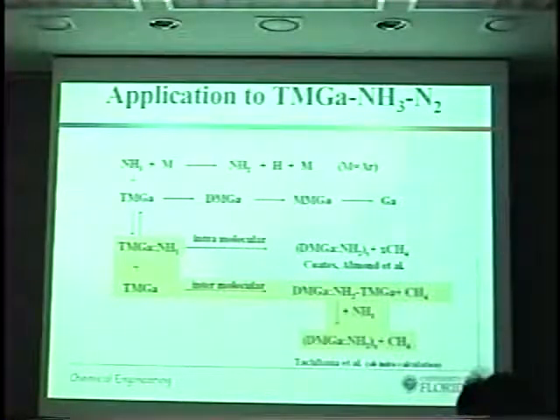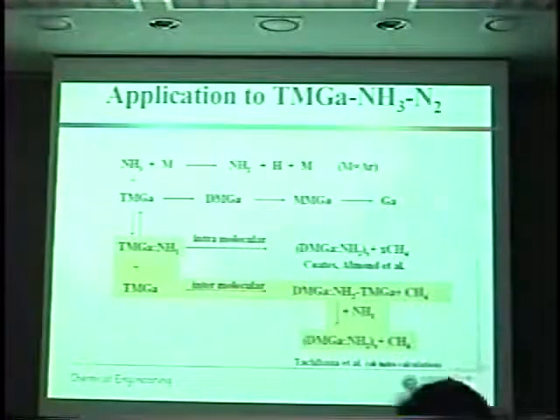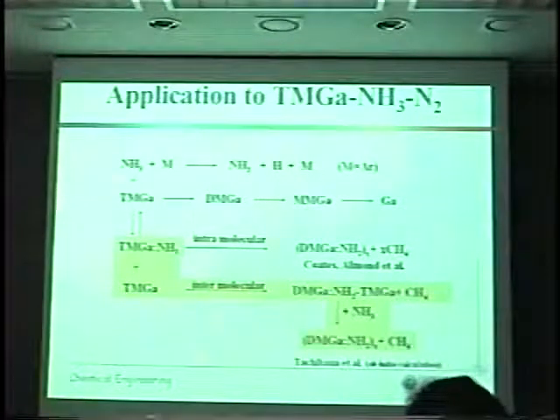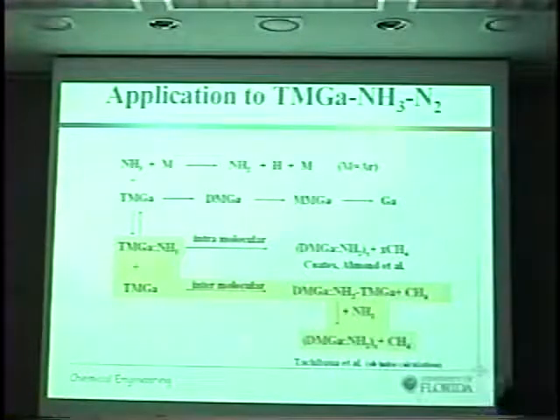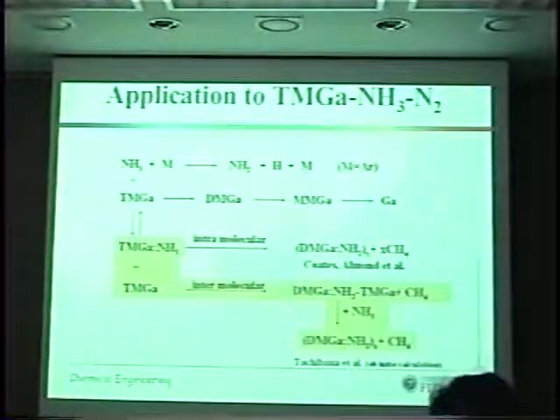And what we discovered is that the trimethyl gallium and ammonia at low temperature in the inlet region are actually forming an adduct. This adduct compound can then undergo further reaction by attack of the trimethyl gallium to form an oligomer, a polymer, and this polymer can coat out on the surface. It can also undergo an intermolecular reaction to produce the same oligomer.